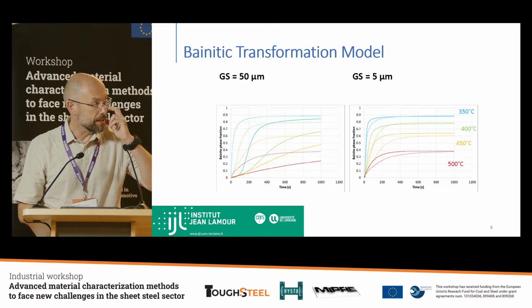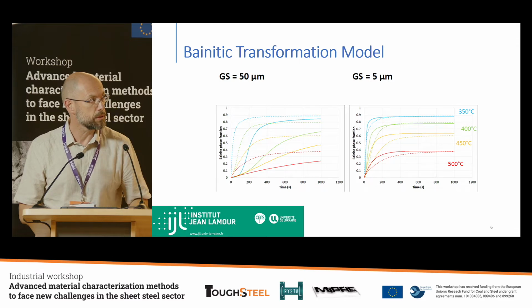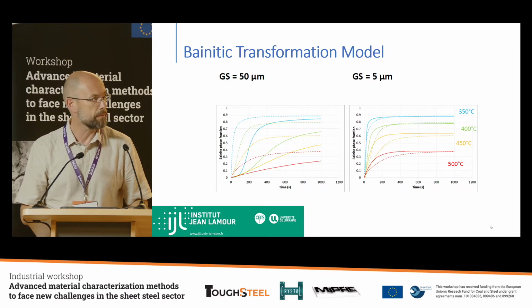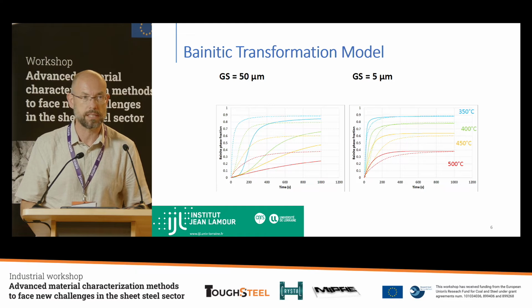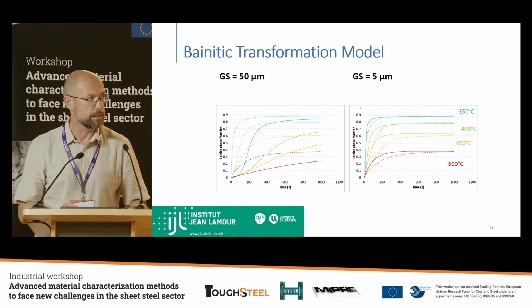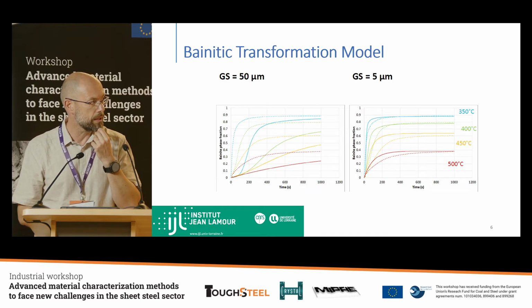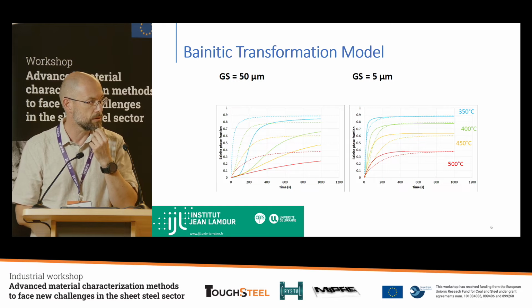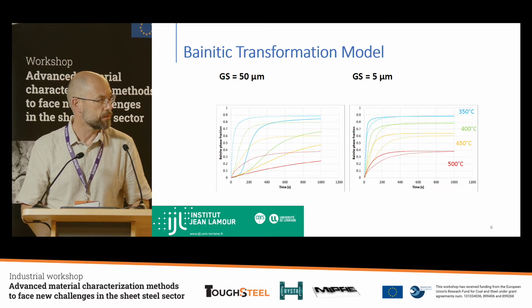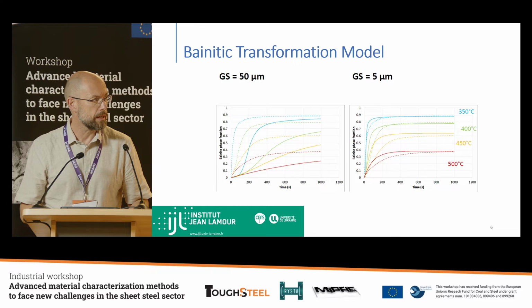And other parts, as I mentioned before, we were dealing with Bainitic transformation models, but also with the martensite and the tempered martensite modeling. Here I put the results that we achieved with the Bainitic transformation model. This work was mainly done at the Institut Jean Lamour in Lorraine, in France. And they actually got nice results because it's a model that can consider the effect of the austenite grain size.